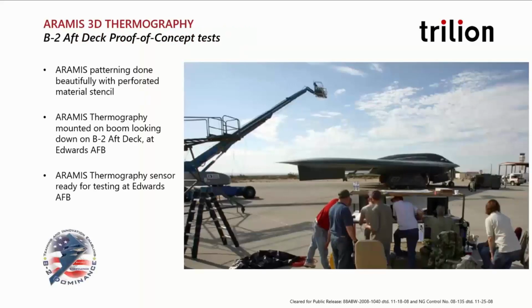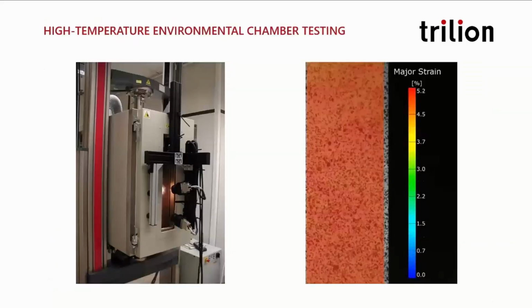One example of this was working with the B2 program. We developed the ability to do digital image correlation and thermography. And so ARAMIS thermography allowed us to look at the aft deck of the B2 bomber with the hot gases flowing across the surface of the deck and look at the fracture in these components. This helped them solve a problem that had been nagging the Air Force for 20 years.